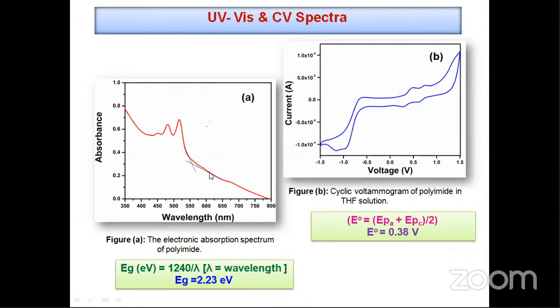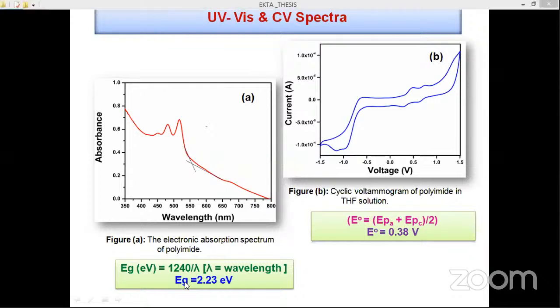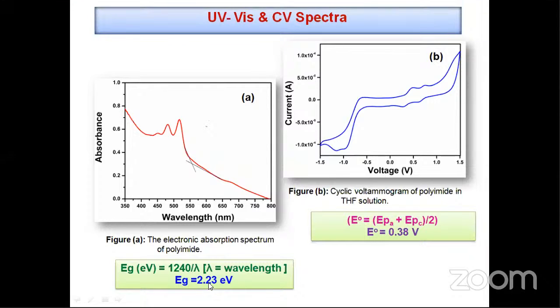Because the onset value is not completely offered, from this baseline value we can calculate the band gap between the HOMO and LUMO energy levels using this relation, that is, band gap is equal to 1240 upon lambda. This lambda is this onset value, and by using this relation, the band gap of the polymer is calculated as 2.23 electron volt.